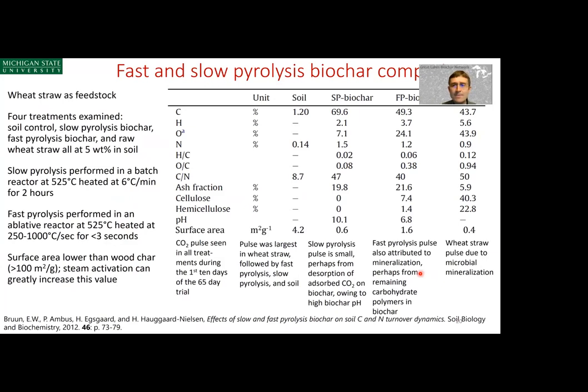So even from the same feedstock, biochars produced under different operating conditions will be different. Here's a study by Bruun et al., published in Soil Biology and Biochemistry, using wheat straw as a feedstock. They examined 4 treatments: a soil control with no biochar added, a treatment that adds slow pyrolysis biochar at 5 weight % in soil, another treatment that adds fast pyrolysis biochar at 5 weight % in soil, and a final treatment that just takes raw, untreated wheat straw and adds it at 5 weight % concentration in the soil.